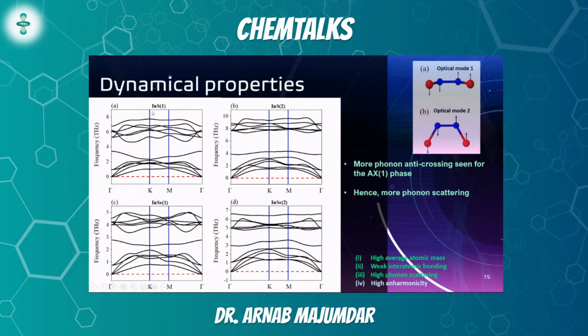Now, for the AX1, which is indium sulfide 1 and indium selenide 1, we can see that there is more phonon anti-crossing between the acoustic branches and the two lowest optical modes compared to the AX2 structures. It's very difficult to actually see the phonon anti-crossing because it has to be highly magnified to point that out. But we actually saw that there was much more phonon anti-crossing in AX1 compared to AX2. And the anti-crossing was happening with the first and second optical modes, with the acoustic modes as well. And we have depicted the optical modes here, if you're interested.